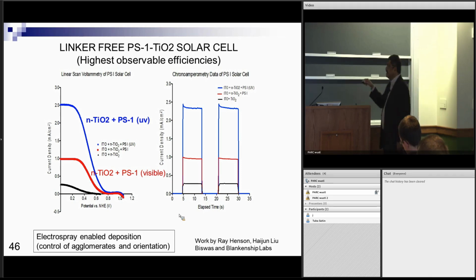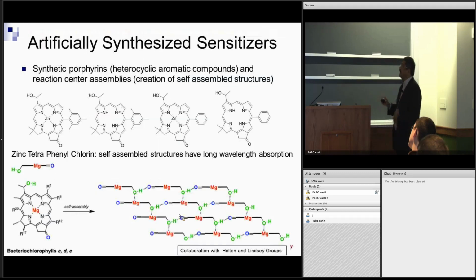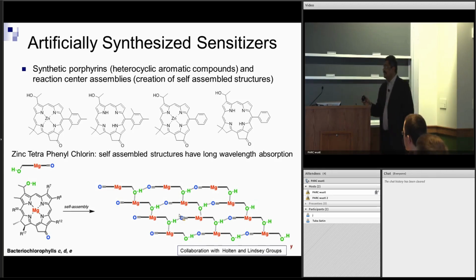But the key is electrospray enabled deposition, controlling the agglomerate size, the orientation now, because this is an entire entity. It has to inject the electron directly into the TiO2. The orientation becomes very critical and so forth. And the currents that he measures are far greater than what has been reported by others, because they again have to use linker molecules to get the PS1 to stick to the semiconducting materials.